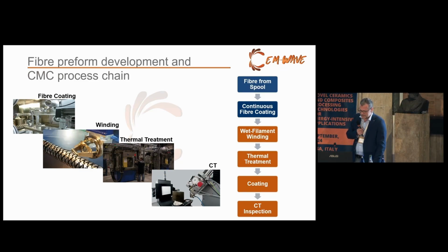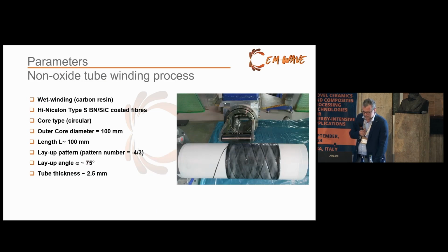And then, of course, a CT inspection has to be done to really look at your sample, because after the long way from the preforming to the end, you can do a lot of things wrong. You can get a complete delamination of your material. You can have oxidizing. You can also have a problem with your oven system when your temperatures rise dramatically, which happens also sometimes in our facility. And this you have to keep an eye on, because everything you do wrong at the beginning, you get at the end in this system.